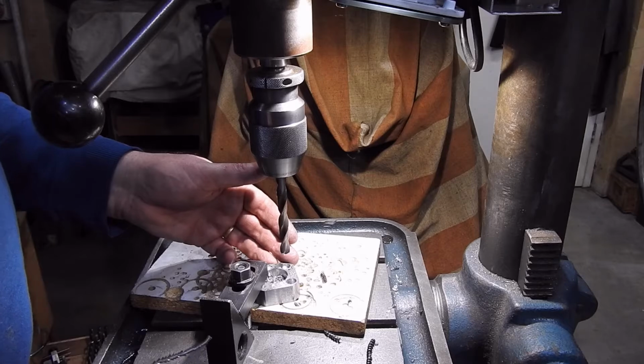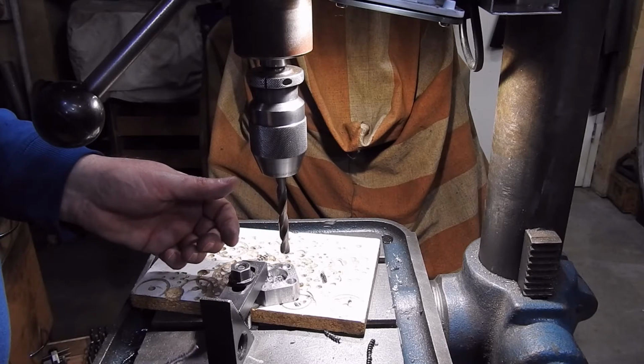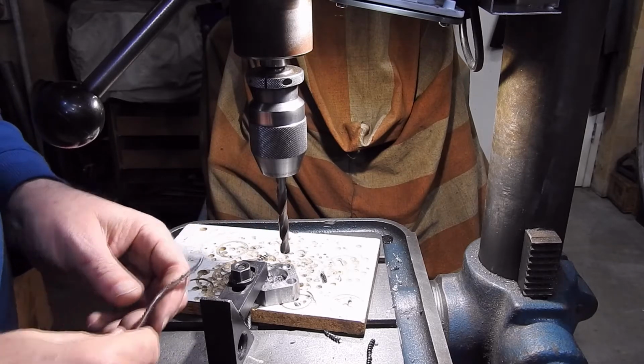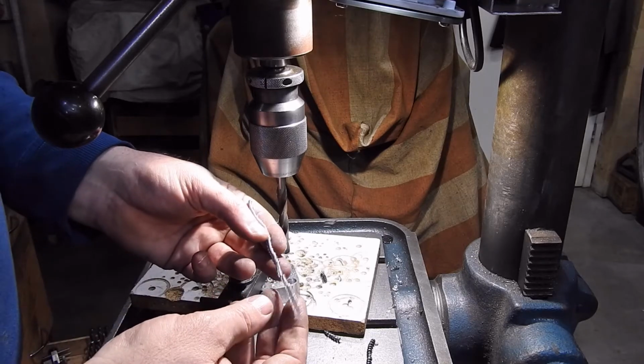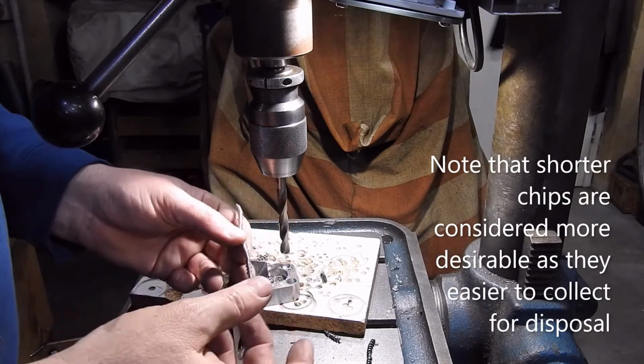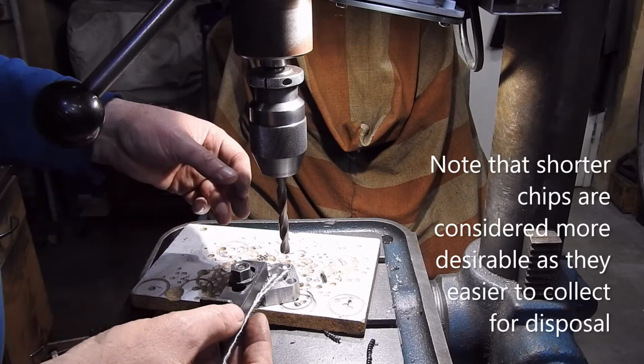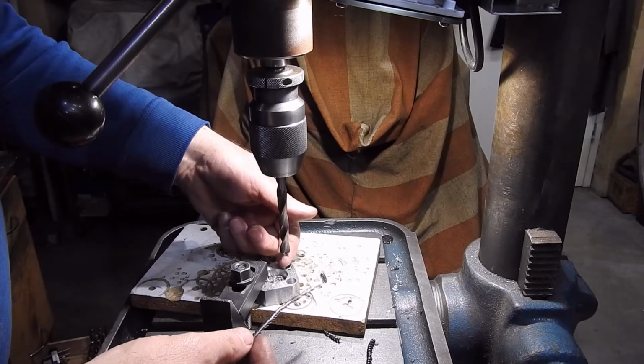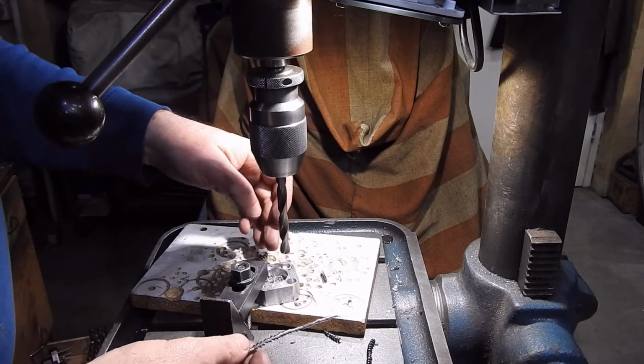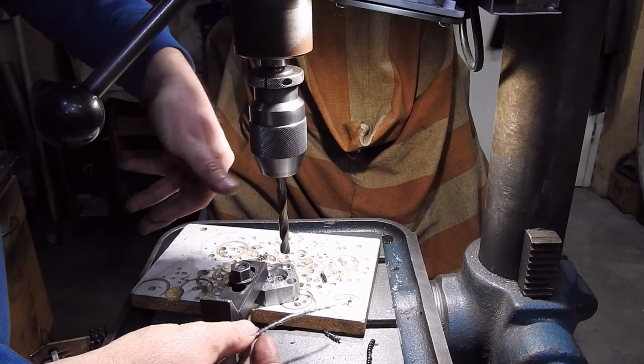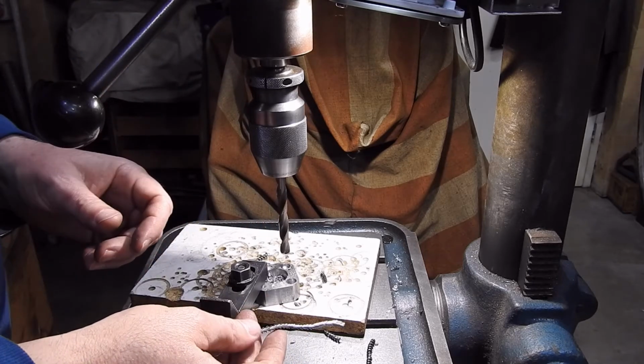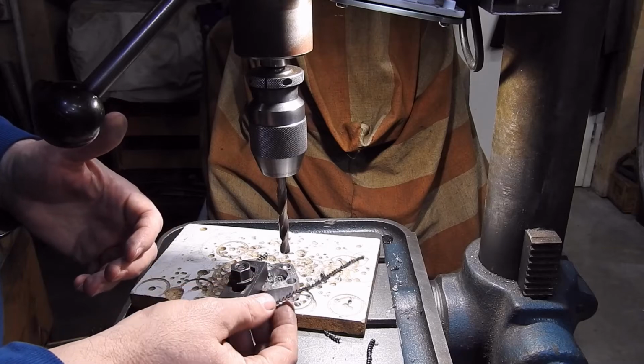This hole is at 260 RPM, so around about a third of the recommended speed. As you can see, the chips are still coming off quite alright. Probably a little bit more pressure. The way a drill bit cuts is that the chisel point is what starts the hole, and so that's scraping as it goes in. So the slower it is, the more it has to scrape to get a decent cut.